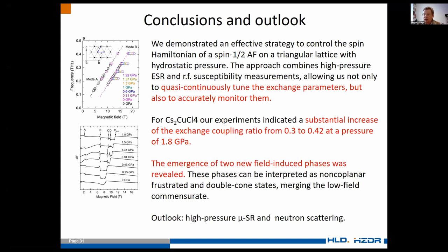This is the setup which I used in Tallahassee, pretty much the same in many other places. But for pulsed field measurements, sensitivity is a very important issue, even if you have quite intense terahertz radiation. It's different, but there are no principal limitations. Okay, thank you. So you also go for antiferromagnetic materials, and this is what we are doing most. Magnetically ordered materials are even better, because oscillation strength is quite big and it's much easier to work with.